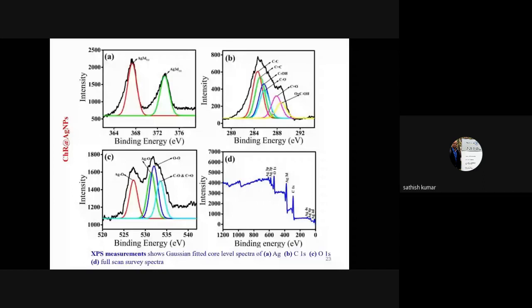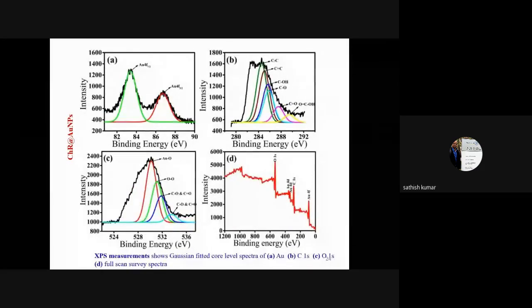Similarly, for gold nanoparticle also, we have observed the core level spectrum at around 86.7 and 83.3, which clearly shows the presence of gold as a major element, and also the other functional groups clearly indicate that the chrysin is being functionalized on the surface of the particles.